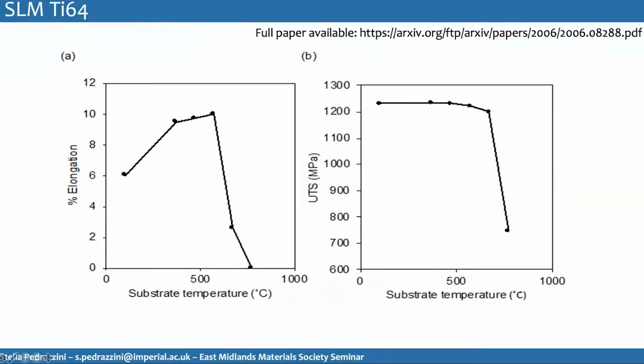This is from a tensile test, elongation to failure. The first sample at 100 degrees had some ductility. Up all the way up to 570, ductility went up, and at 770, the ductility was 0, and the sample was as brittle as it gets. It was basically failing like a ceramic. And the UTS, you can see the exact same thing at 770. It just went all the way down, which was quite interesting.